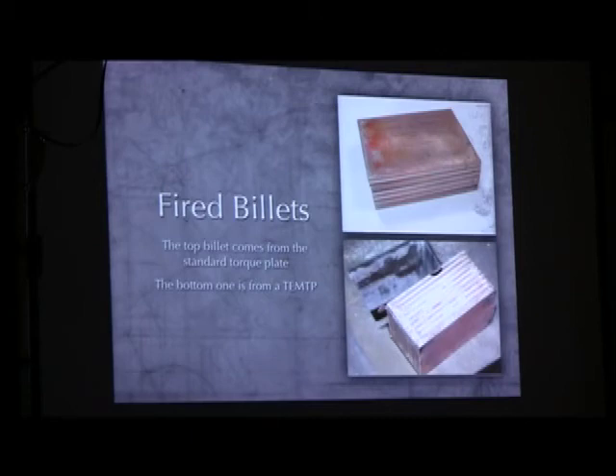But one of the big problems when you're working, especially in gold, is to trim that edge back to get those all nice and flush after it's bonded. You can lose 25 to 30% of the mass of that billet just removing 1.5 millimeters around the periphery. So even when gold was $300 an ounce, that was not so good. If you look at the one on the bottom and look at how it's filled the cavity, you don't have that stair-stepping or jagged edge. That's a great advantage. And I don't know if you see these spots here, the pressure increased so greatly inside of that system that the red gold actually extruded out between the gaps in the torque plate. So we got the pressure we were looking for.